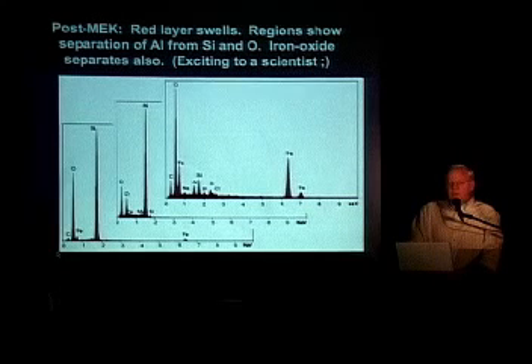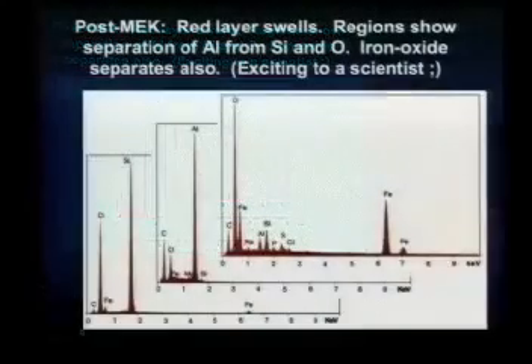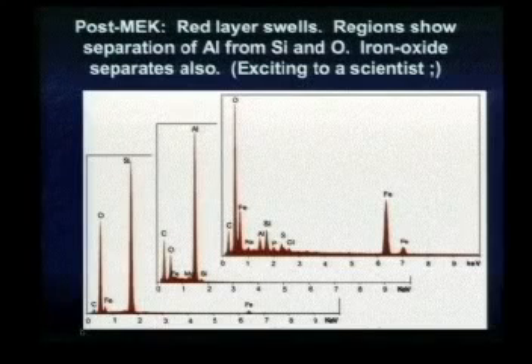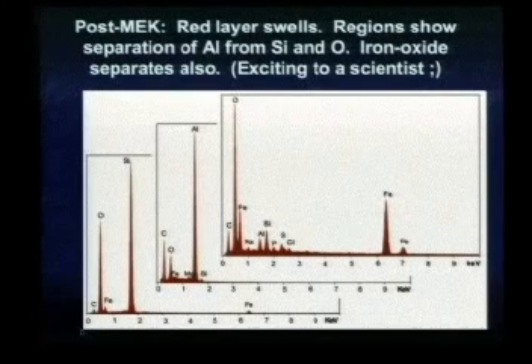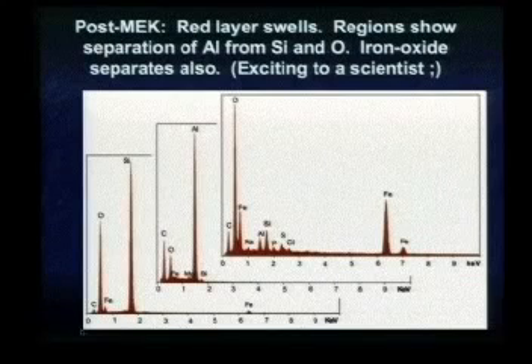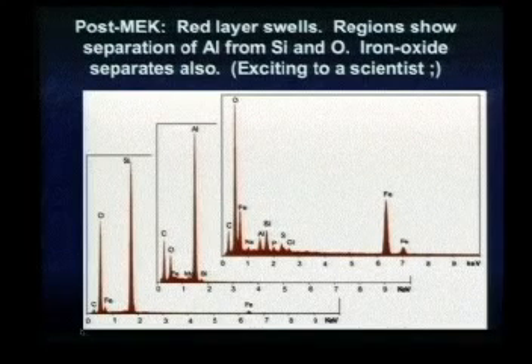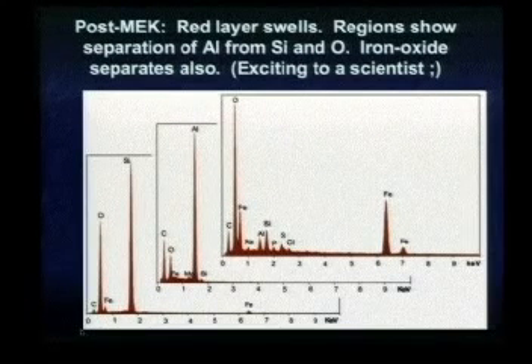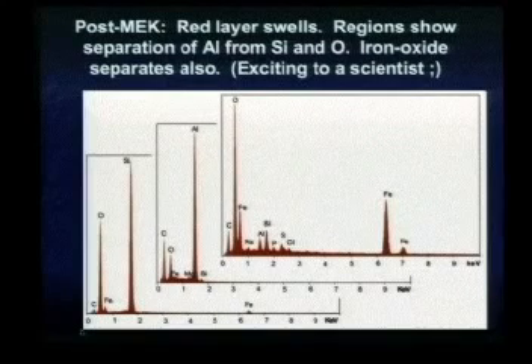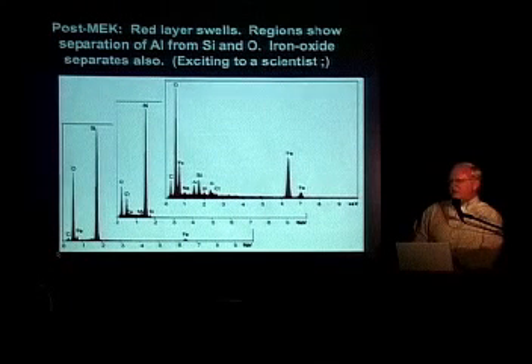After the MEK soak, we now see regions where we see aluminum separated from silicon and oxygen. If you look at the leftmost plot, you see the silicon and oxygen, a little bit of iron, essentially no aluminum. This is not aluminum silicate. It's not kaolinite, as some debunker said. Oh, it's kaolinite, that's all it is. No. You can't use a paint solvent and separate the aluminum from the silicon oxide in an aluminosilicate. It's just a solvent. It's not a reducing agent, okay?